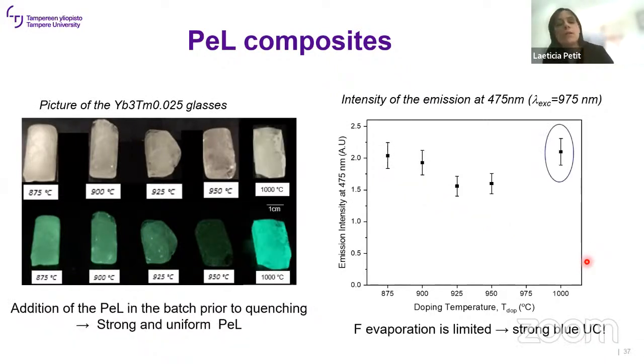So we had to change the way we prepared the glasses. We melted the glasses at 1000 degrees C, and we added the persistent luminescence right before the quenching. So we could reduce the fabrication time for the glass. And we had to work on how to disperse the particles, so it was some manual mixing of the batch. Then you can see that we have a very strong and uniform persistent luminescence, even if we use a high temperature, so we know how to disperse the particles. And because of the shorter preparation time, we have a high intensity of the blue upconversion.